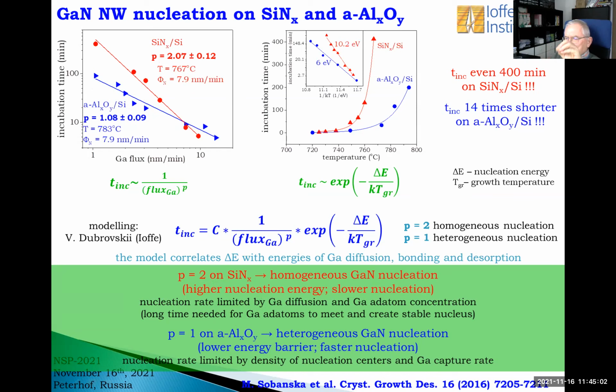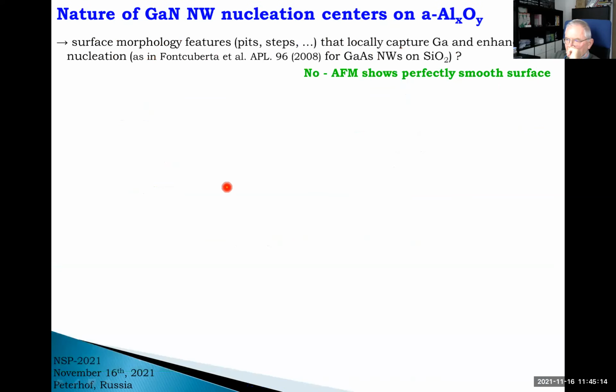So gallium nitride nucleation is heterogeneous, and nucleation rate is limited by the density of those centers and their efficiency to capture gallium. Okay, so we see the difference between these two cases. One is homogeneous nucleation, the other one is heterogeneous nucleation on aluminum oxide. The question is, what is the nature of centers that induce nucleation of gallium nitride on this aluminum oxide film?